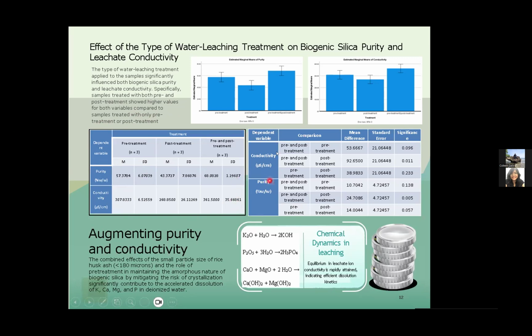So kasi both siya, ayan, yung pinakamataas talaga is ito, yung pre-treatment, tsaka dito sa conductivity pre-treatment. Tapos second is both pala. Tapos second is pre-treatment. And then third is post-treatment, yung pinaka-lowest. So it's an evidence of augmenting purity and conductivity, that the combined effects of the small particle size of rice hull ash, kasi sa post-treatment, ash yung tinitreat mo, which is less than, sabi sa literature, 180 microns.